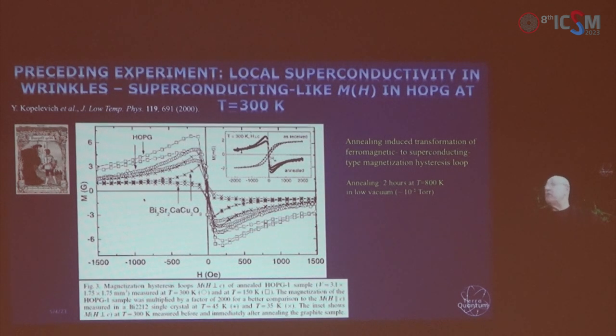And those were beautiful experiments which actually established the existence of local superconductivity in graphite samples, even at room temperatures. So those are magnetization hysteresis loops measured when the magnetic field is perpendicular to the graphite planes.